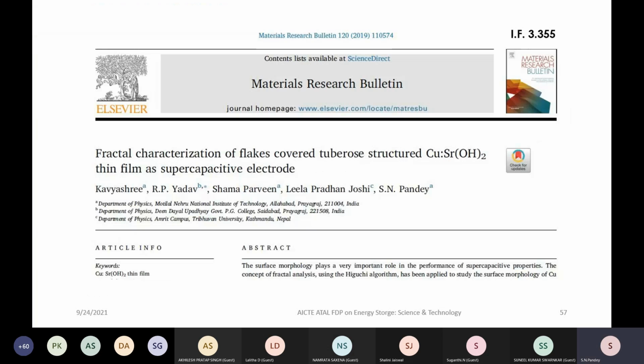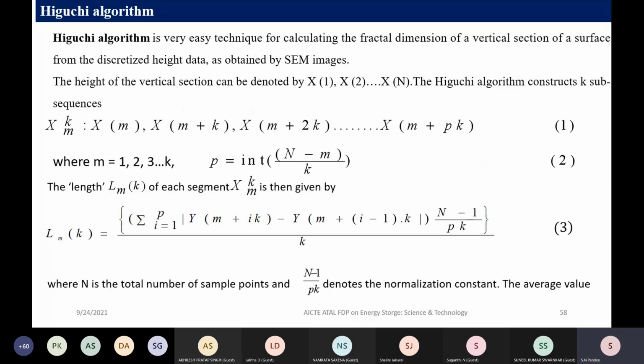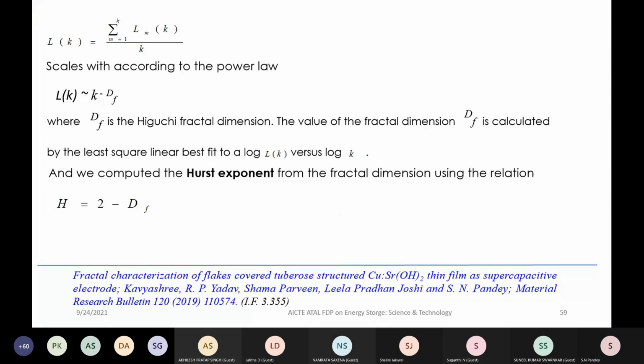So we have used copper doped strontium hydroxide and made the fractal characterization. We used the Higuchi algorithm, and Professor Lakshmanan has already given a deeper idea about this. With its help, one can calculate the fractal dimension and the Hurst exponent, and we obtained this type of result.